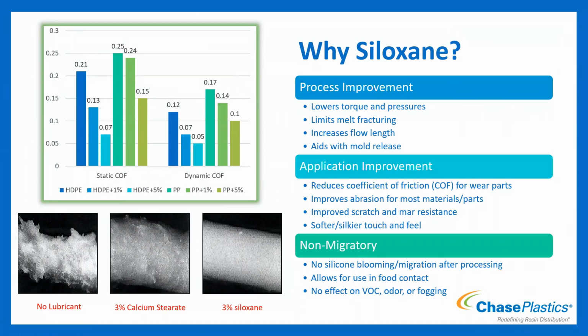Okay. You can also help with flow length because it's going to flow a little easier. It helps with mold release. So if you're having issues with releasing from the mold, it can help with that as well. And then when you add enough in, you can start to affect the actual application itself, not just the process. Once you add enough in, because it will get to the surface, and we'll show that in a couple slides, you're going to reduce the coefficient of friction. So if you're using it in wear applications, maybe a gear, maybe something that's wearing up against a metal shaft, whatever it may be, if there are moving parts, this can lower your COF, so it wears a little easier, produces less frictional heat, and has a longer life cycle for the part itself.